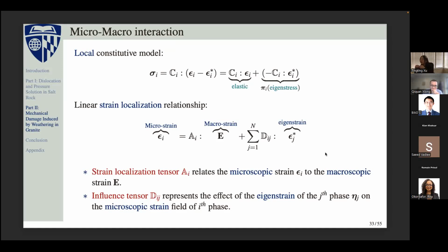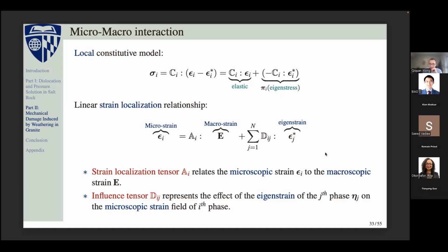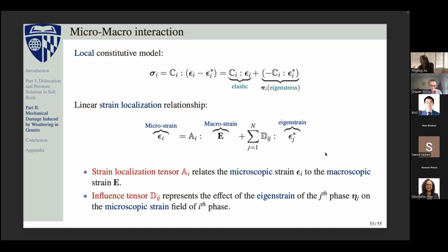And here we will have this local constitutive behavior. The top equation is the local constitutive behavior of the biotite. So it has two terms. The first one is the elastic term, and the second one is the inelastic term. That corresponds to the eigenstrain, and we define it as the eigenstress term. And the second equation, the bottom equation, you can see is the relation between the local behavior, the microstrain, and the macrostrain. So still, it's very similar to the content that I introduced before. It's a linear relationship, and it has a fourth order tensor A, which is a strain localization tensor.